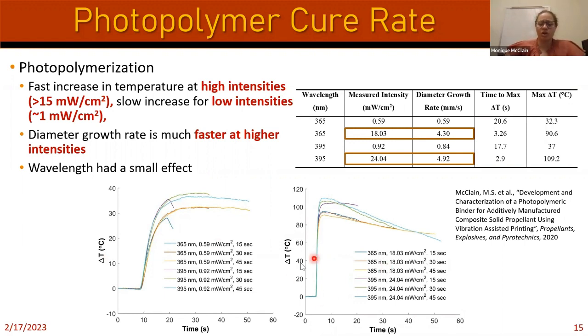However, when we use the high intensity conditions, we can see that it rapidly begins curing and increasing in temperature. And we could see that, okay, 15 seconds is probably long enough to get it to react. And then we can see that as we just leave the light on longer, all that's happening here, well, not all that's happening, but in general, it's starting to cool because it's so hot. But in general, when we applied the light, we kept the light on the entire time for these test conditions.